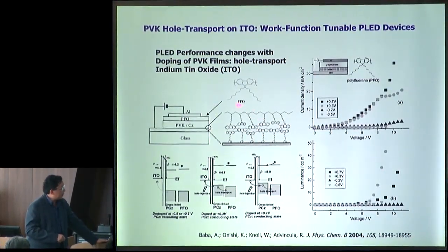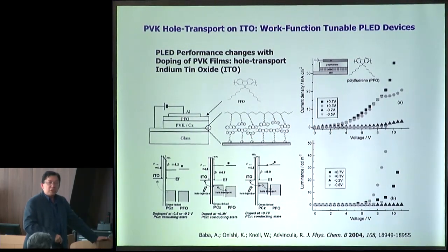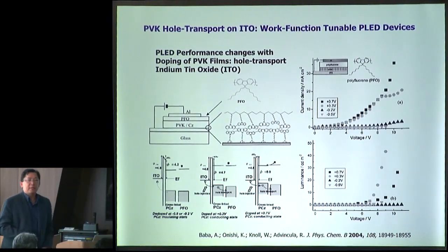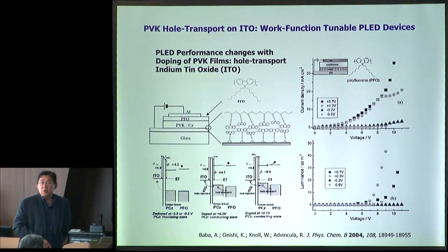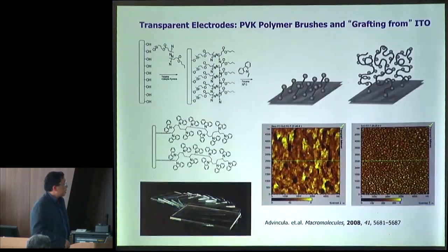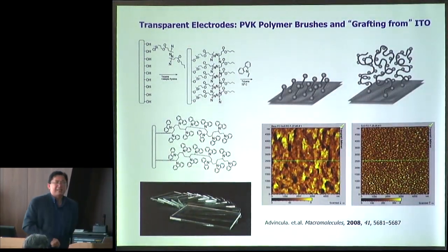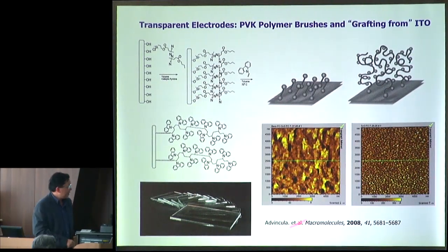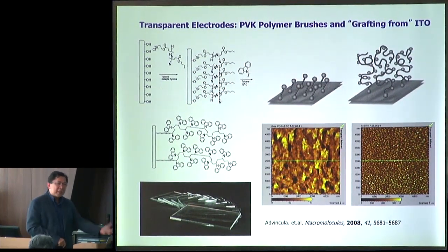For example, very early on, with LED material based on polyfluorene, we can change the turn-on voltage and the electronic properties by tuning the properties of this oxidized polymer and then seeing how it changes the function with respect to ITO. ITO is a very important substrate, as most of you know or have used, because it's a transparent electrode. But when you get an ITO, it looks like this. It's ugly. It's rough. And in order to use it, you sometimes have to clean it.